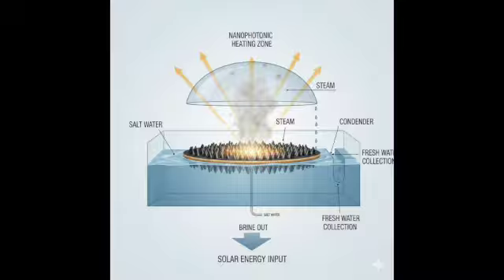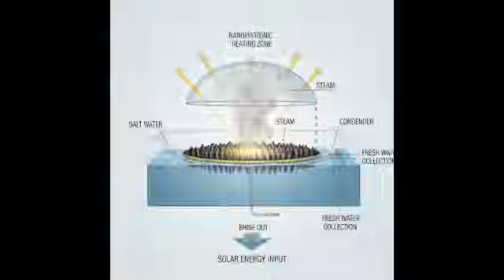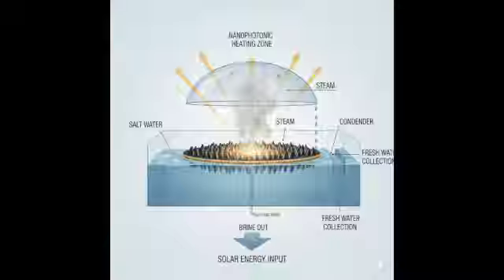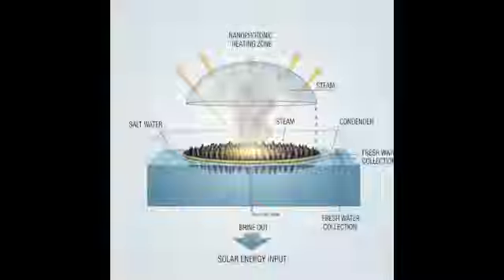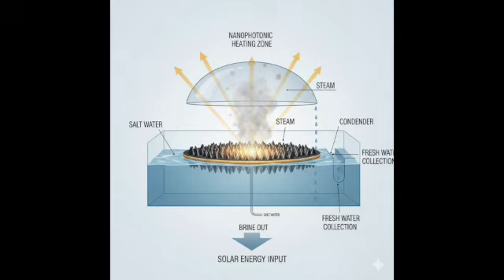Okay, that context is crucial. Now, what about the bottom line, water production cost? This is where it gets tricky, and the data varies widely depending on the scale, location, and specific technology assumptions. Traditional large-scale desalination costs are roughly $0.5 to $1.5 per cubic meter for RO, and maybe $1 to $1.4 for MSF. And MD? The reported costs for CMD have a huge range, anywhere from around $0.5 per cubic meter in ideal scenarios with waste heat, up to over $15 or more for smaller or less optimized systems.